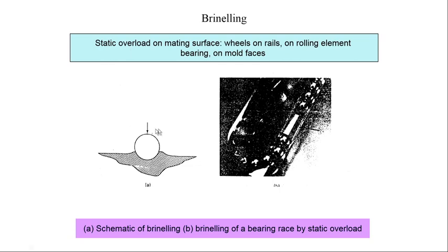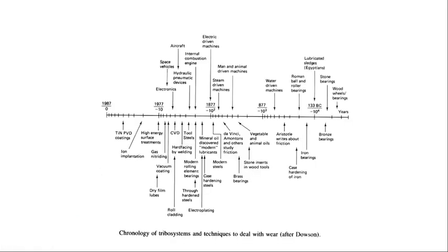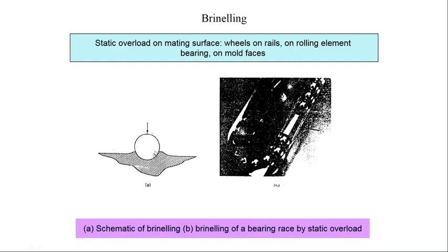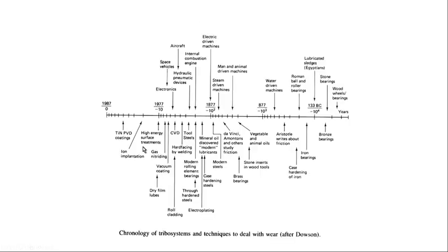So, that is of no use, so naturally you have to repair it. Again, this is the loss of the component. If you are interested in getting rid of brinelling, then again you have to avoid the typical impact phenomena, or otherwise you have to apply a very thin elastomer on the surface, which is a shock absorber and subsequently reduces the probability of brinelling wear in actual service.